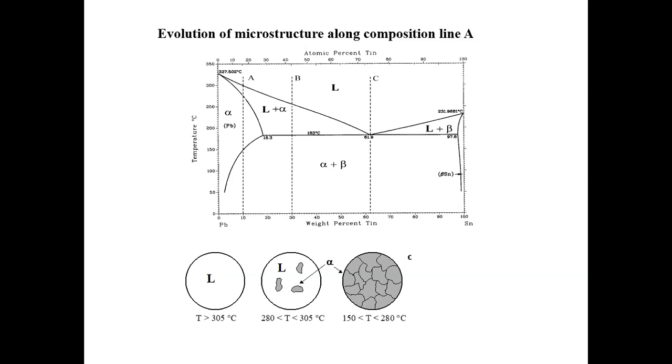Okay, so there's one more thing. If I give you this alpha structure, the difference from the sugar water example is that there you have solid precipitation from liquid, and the solid will eventually settle down to the bottom of the container. But here, we're talking about precipitation in a solid solution. So where do you think the precipitation is going to occur, and why? Along the grain boundaries, right? Or on the triple points. They have a high probability of occurring at these defects, right? Does this make sense to everyone?